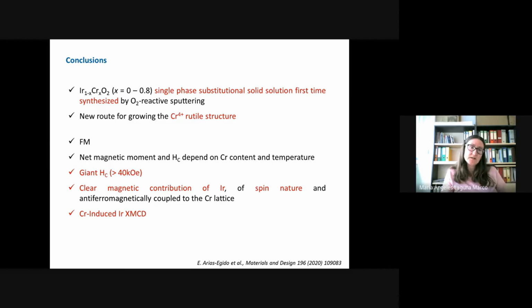The XMCD reveals a significant contribution of the iridium to the magnetic response of the films, and in addition, it reveals mainly a spin character of the magnetic moment, which is very different from that typically found in other iridium 4+ oxides, and strongly suggests that this iridium moment is induced by chromium. This is quite a remarkable and surprising result for an oxide.